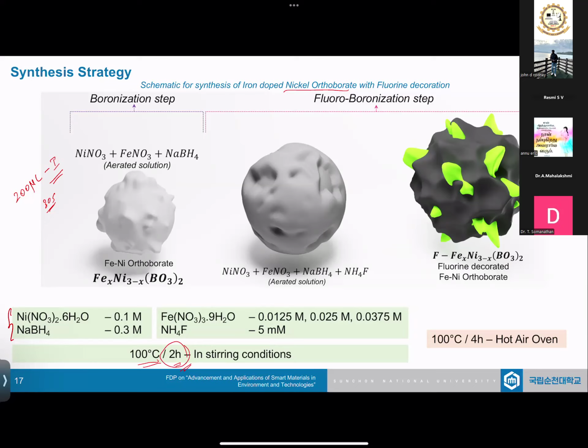We didn't purge any argon gas or nitrogen gas or anything into our solution, because we wanted the oxygen to be present there so that we can get a proper orthoborate system rather than a nickel boride. So what happened in that aerated solution, we finally developed nickel orthoborates.